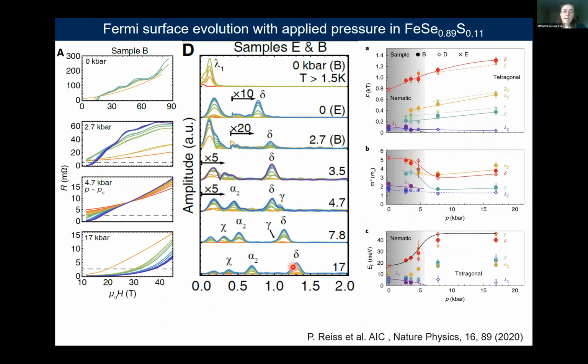And the same effect happens with chemical pressure, but also with applied pressure. So here with applied pressure, we again tune across the nematic phase from about 0, 4.7 is about close to the critical pressure. And again, we have a very slow frequency here, but that slow frequency is gone outside the nematic phase. And it's represented by this lambda pocket in the frequency versus pressure phase diagram. Most of the frequencies increase with pressure or chemical pressure, but this particular one seems to disappear at the nematic phase transition.